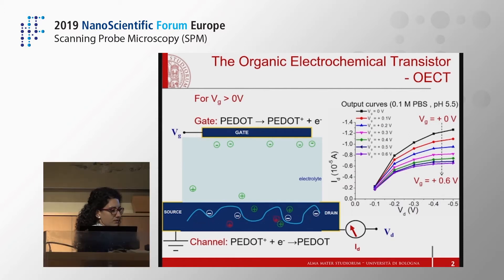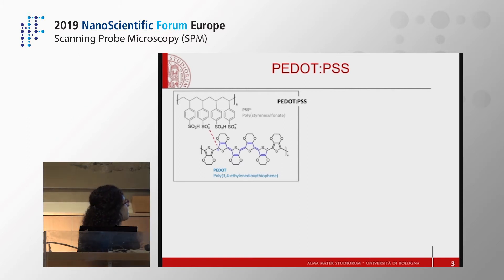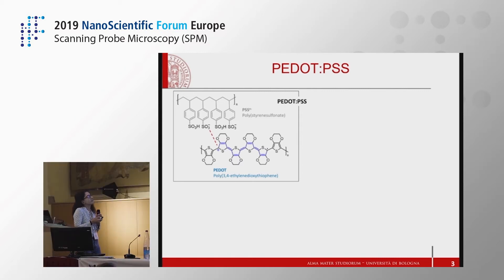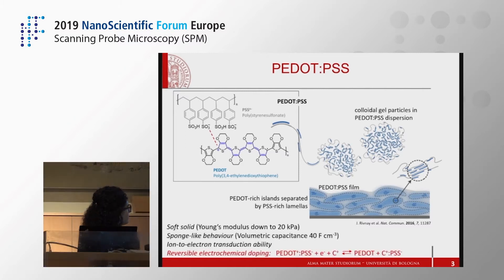The main features of these devices come primarily from their major component, the semiconducting material, typically in our case PEDOT:PSS. It is a polyelectrolyte complex of a p-type semiconducting polymer PEDOT and PSS, which is a polyanion that stabilizes the conducting form of PEDOT, which is PEDOT+. When deposited as thin films, PEDOT:PSS is organized in a pancake-like structure as a blend of electronic and ionic microphases, capable of reversible electrochemical doping by exchanging ions with the electrolyte.